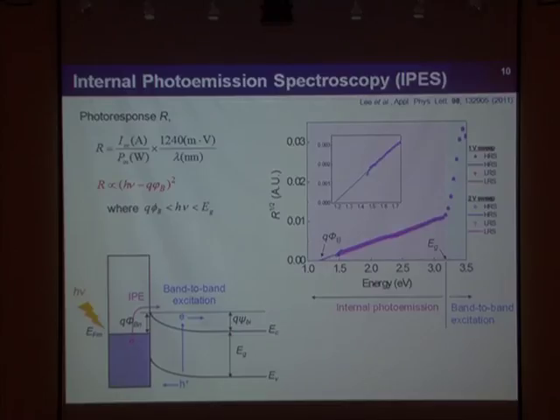When we prepare samples with different resistance states using different polarity and magnitude bias voltages, in all cases the barrier height is nearly the same. So we cannot observe any change of the barrier height.